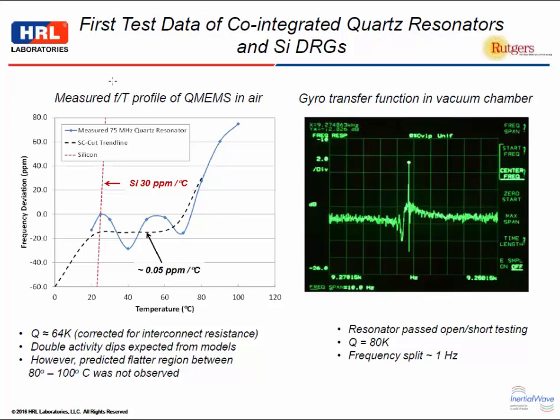On the silicon side, the resonators passed. There's a lot of possibilities for opens and shorts on these complicated structures. They passed mostly the open short testing. The Qs were around 80,000, which was comparable to what we've seen on just standalone silicon DRG devices in a vacuum. And the frequency splits were actually very good, around 1 hertz, and these were operating around 15 kilohertz. Actually, this one's more like 10 kilohertz, I guess. But typically they operated around 14 kilohertz.